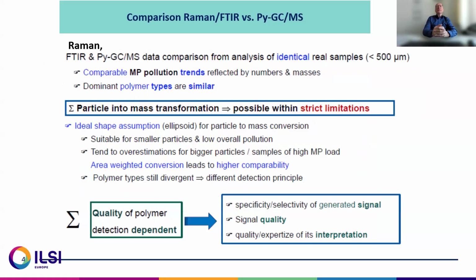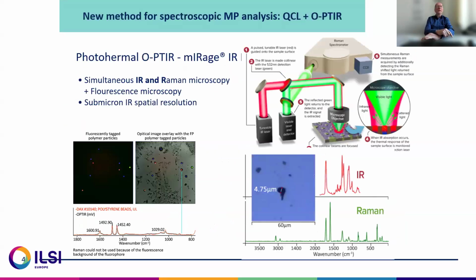We tried this comparison for identical real samples. We had a comparable pollution which reflected numbers and masses. The polymer types, that means the identification, is very similar. That is good. However, the quantifications can be problematic because particle-into-mass transformation is possible, also with strict limitations. You have an ideal shape assumption for the mass conversion. That this is not really true. And so we have a trend to overestimate bigger particles. This is in progress, how we can improve it. And then in Pyrolysis-GCMS, we have very selective generated signals. The signal quality is sometimes, at low detections, also not so good, and the interpretation of the signals is also not clear for all polymers.